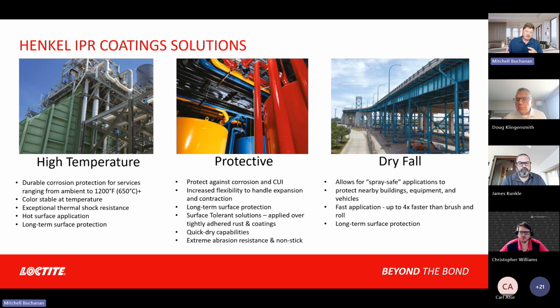Above 320 Fahrenheit, the water typically flashes off very quickly, any moisture entrapped in the insulation. Now, if it's absorbent insulation like mineral wool, it won't fully dry out typically, but you're not super worried about corrosion while the equipment is operating above, say 350, 400 Fahrenheit. But in shutdown, startup cycling, right, you get below that 300 Fahrenheit, and now you're back in that rapid corrosion environment.